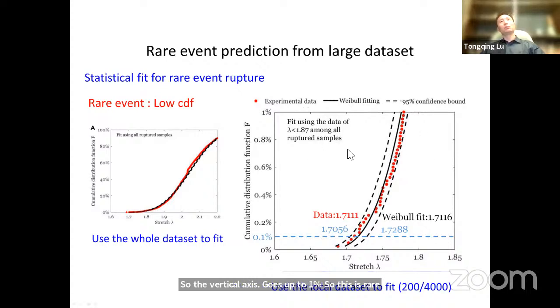To predict the rare event rupture, of course, we need to do some Weibull fitting, because experimental data is discrete. So we want to fit to have a continuous line to predict any event. But when we do fitting, there's a trick. If you use the whole data set to fit, you will see the fitting is not good. Our collaborator, Professor Jose from Stanford University, taught us a way for better fitting. The idea is just to use the local data set to fit. For example, from the 4,000 rupture data, we use the first 200 data to fit. Then we get a very good fitting.